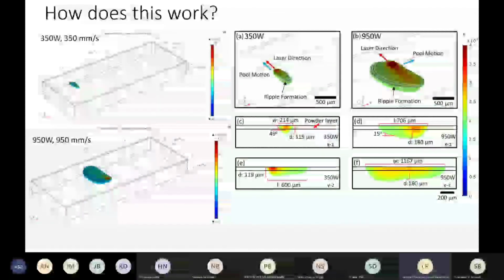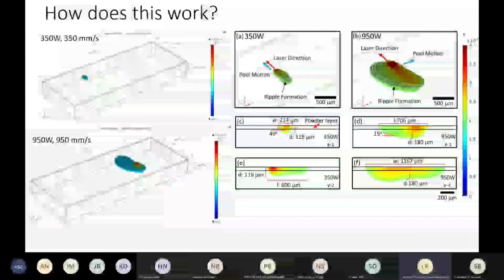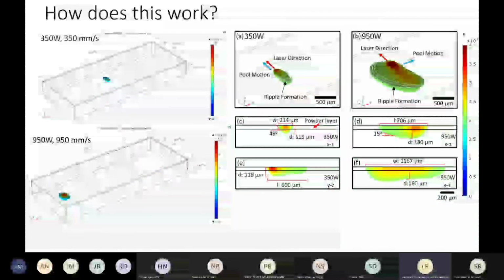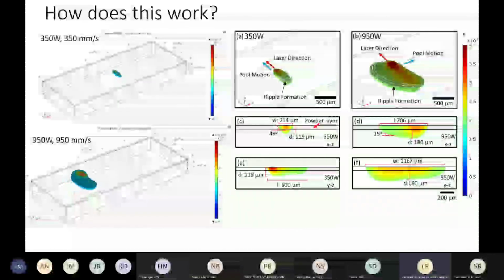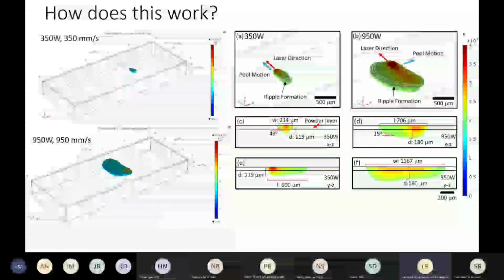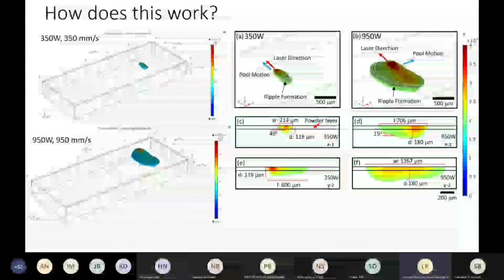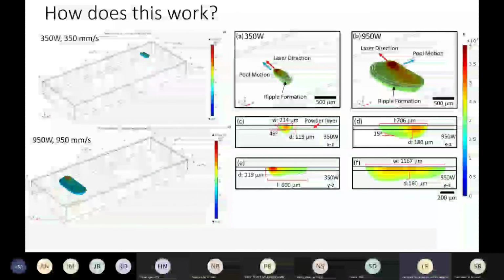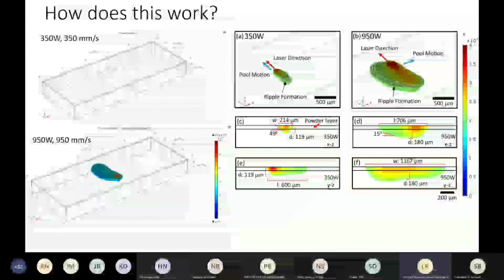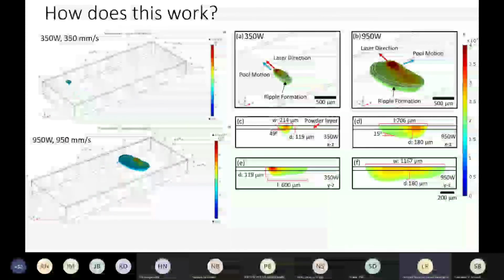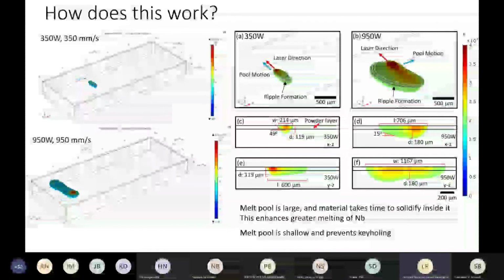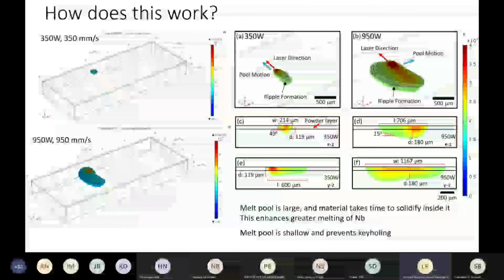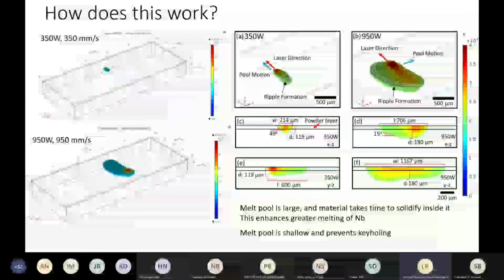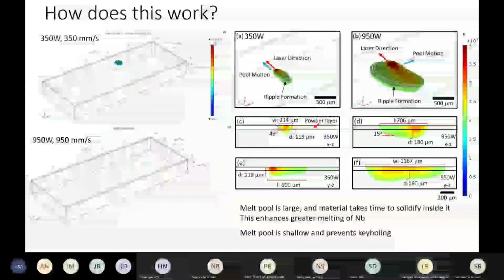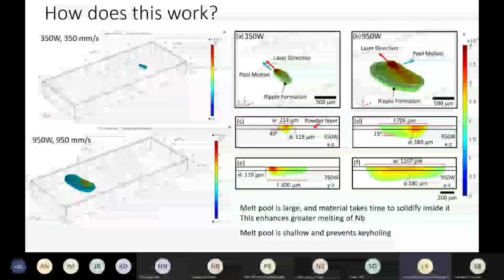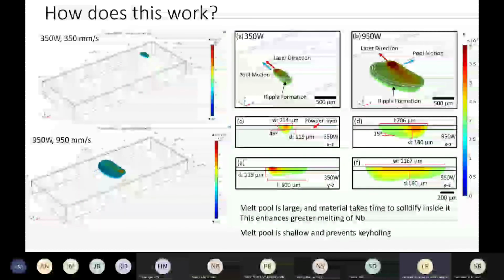The other aspect you see is that the melt pool aspect ratio of the second strategy, the 950 watt strategy, is much lower, which is very important because keyhole porosity can be prevented. So one is that by increasing the speed in the stripe scanning strategy, you are actually melting more material for a longer time, allowing homogenization, which reduces the niobium content. And then you finally make the melt pool shallower with this strategy because it does not stay in the same place, and that allows more material to not only dissolve or diffuse, but it also allows your keyhole to not occur.